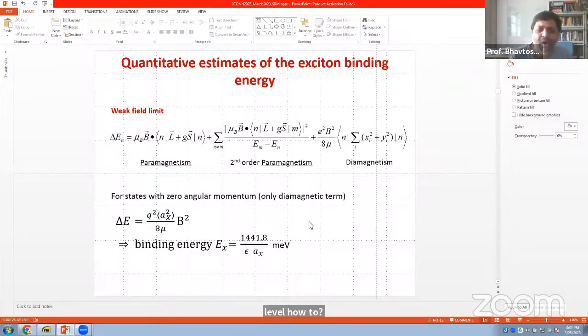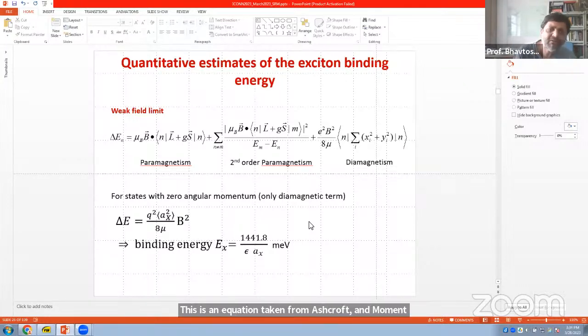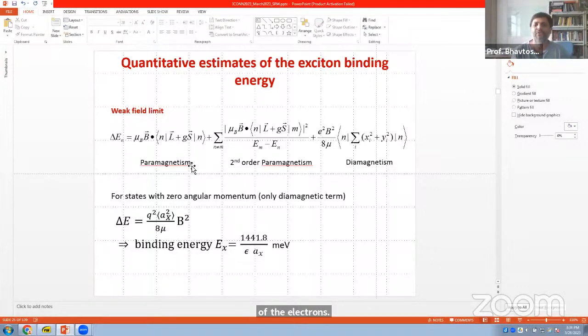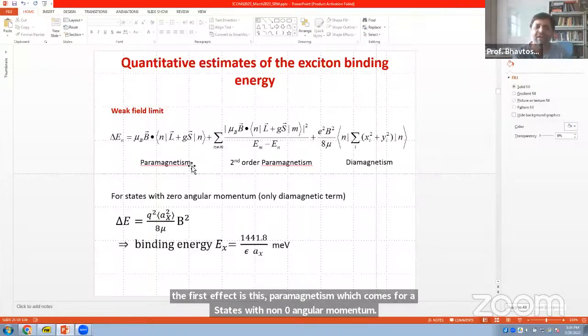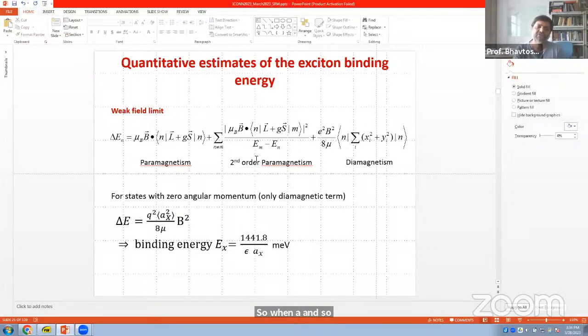This is an equation taken from Ashcroft and Mermin, from the chapter on magnetic properties of materials. Basically, there are two kinds of effects which happen when you apply a magnetic field onto bound states of electrons. The first effect is paramagnetism, which comes for states with non-zero angular momentum, and there are two terms for that. But when you're looking at the ground states, the angular momentum is zero, because you're looking at S levels. So in that case, only this diamagnetism term survives.